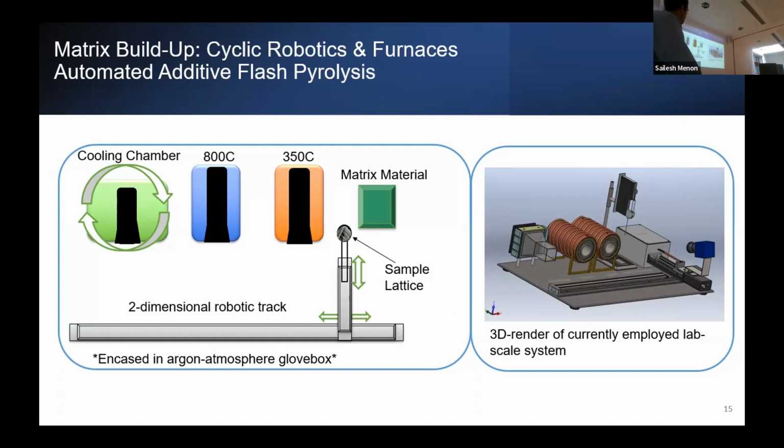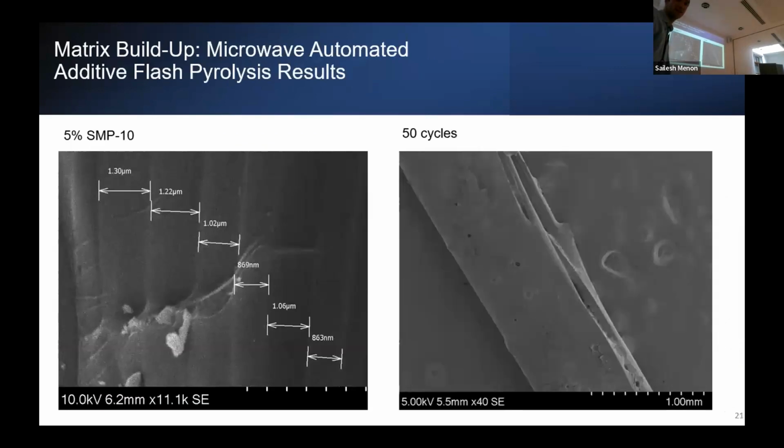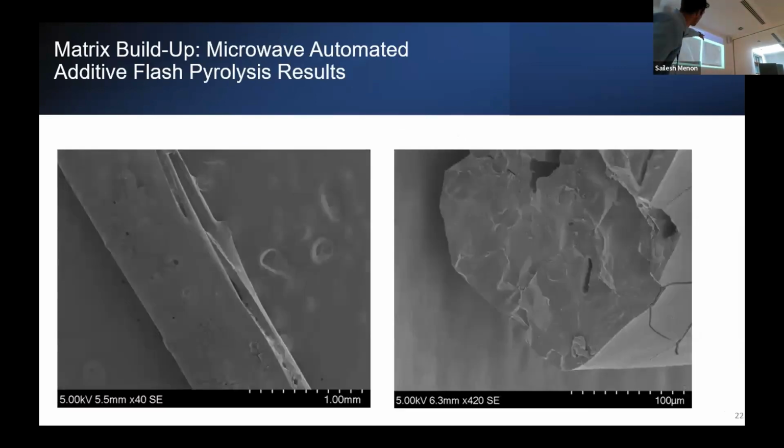So I would say, make sure there aren't any impurities. But also, we're just taking these single tows at the moment, and because it's not woven and we're not holding them tight together, the distance between the fibers can be huge. So right now, with the samples we're actually making, there's probably a fairly large distribution, because we're going to get fairly large porosities from fibers that are not close together, simply because that's how we're fabricating it right now.